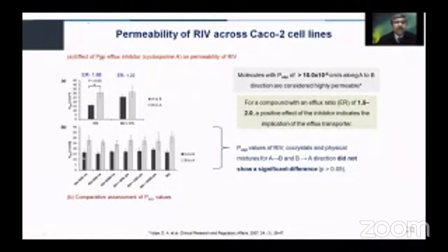Then we compared all the co-crystals and their physical mixtures, and we found that there was no significant difference in the apical to basolateral or basolateral to apical permeability of the co-crystal candidates, which means there was no impact of the co-crystallization on the permeability of rivaroxaban.